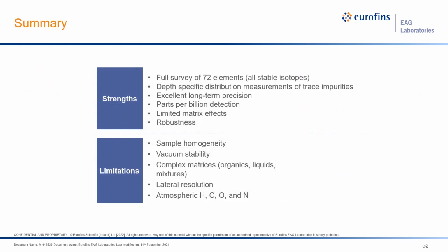In summary, GDMS has a lot of strengths. It is a full survey of 72 elements. It provides depth-specific information. It has exhibited excellent long-term precision for production support. It can reach parts per billion detection limits if needed. And one of the important features is it has very limited matrix effects, allowing analysis of samples without strict matrix matching standards. And it's a very robust technique as a direct solid sampling technique.